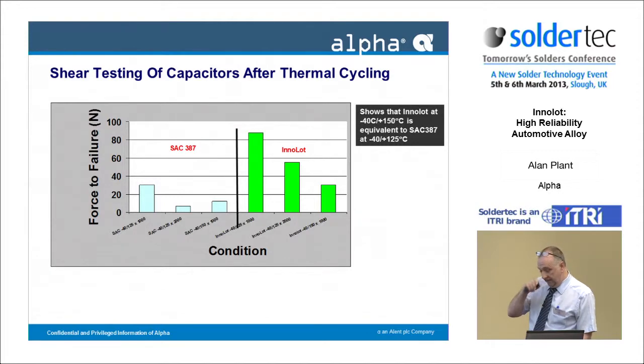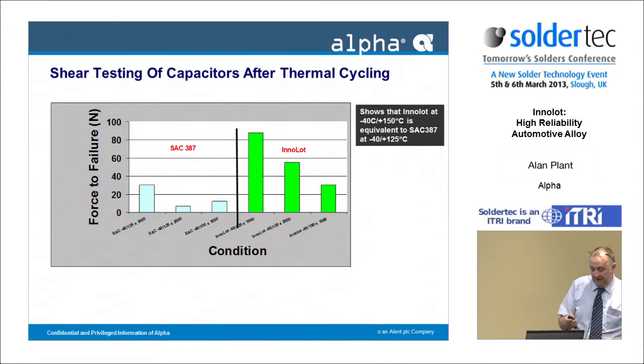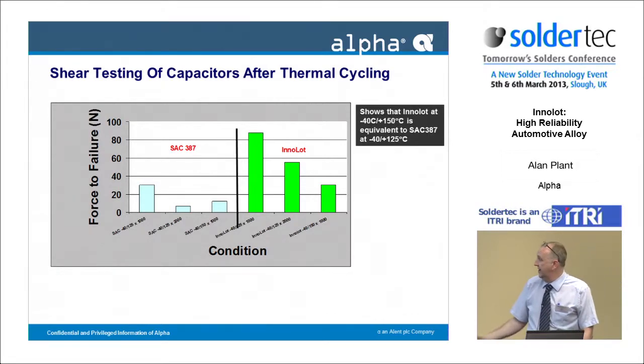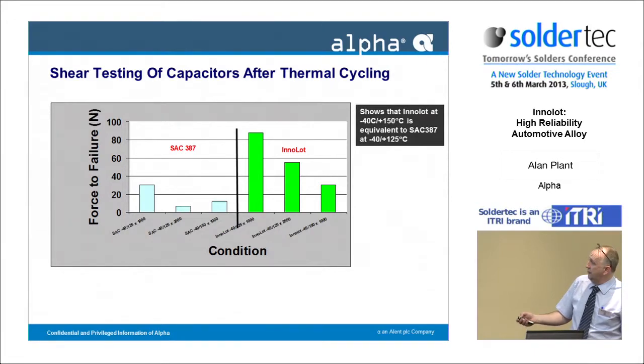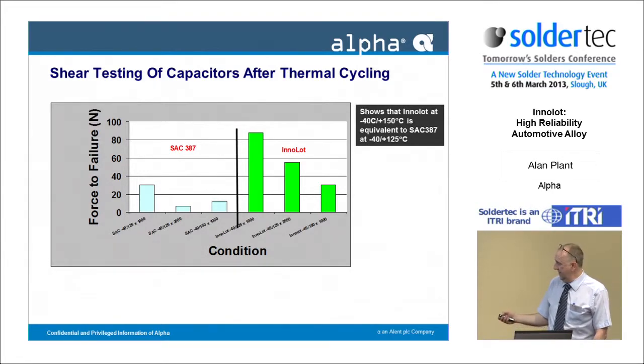A measure of shear testing of capacitor components again after thermal cycling, and the reason people are doing this is because obviously you do get some degree of joint damage, and it's trying to assess how much of the joint integrity has been lost, how much is left after it's been shake, rattle, rolled, or thermally cycled in this case. And here we've got 2 sets. That's -40, 125, 1,000 cycles, -40, 125, 2,000 cycles, and -40, 150, 1,000 cycles, i.e. the target condition. And then the residual force to shear the components off. Whether it's the amount of residual joint or the inherent increase in shear strength of the alloy, I'm sure it's a bit of both, but the Innolot does show a higher residual strength.